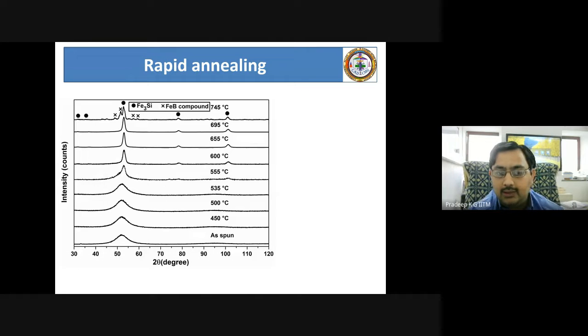Now, if you want to understand the evolution of the microstructure at this nanometer scale, then we have to systematically look into the microstructure evolution. Like I said, the as produced sample is in an amorphous state, and you start heating this material at different temperatures. All that is used for application is more or less in this temperature window, where we are interested in retaining only this iron 3 silicon soft magnetic phase and no other phase, because these are hard magnetic compounds which will interfere with the property of the soft magnetic phase. So the ideal scenario is to have the soft magnetic phase at a nanometer scale retained in a large enough volume fraction within this certain temperature window.